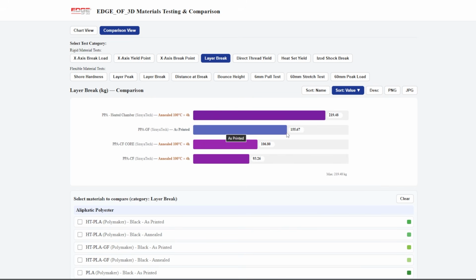Layer adhesion, PPA glass fiber, 155.67. Very respectable numbers. 219.48 on the straight PPA with no inclusions. And so let's discuss that for a minute. When you include things like carbon fiber, glass fiber, anything other than a polymer or a modifier that blends with a polymer, those inclusions help with some things, but they also can take away from other things. So it gives a place for the stuff to break.